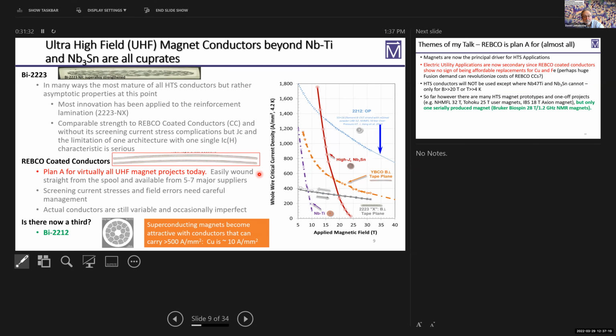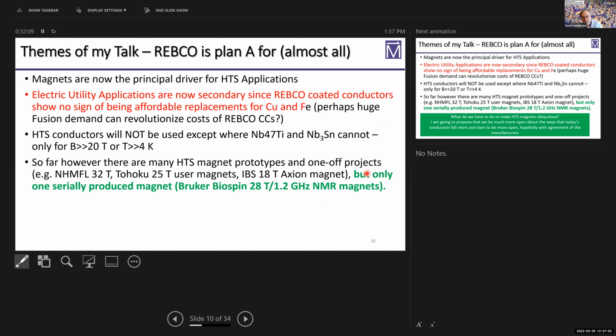So the other issue is to say this, that superconducting magnets become attractive with conductors that can carry 500 amps per square millimeter or so. Copper is about 10 amps per square millimeter. And so you see, if we draw a line across here, bismuth 2212 definitely fulfills this. This I should change. REBCO is up here, especially parallel to the AB planes, which is where much of the magnet operates, but in fact, it is determined by the worst in the end. So the theme of my talk really is this: REBCO is plan A, because you buy it, it's superconducting, all you have to do is respect the fact that if you wind it on too tight a bend radius, you'll crack it, and then you won't have superconducting continuity.